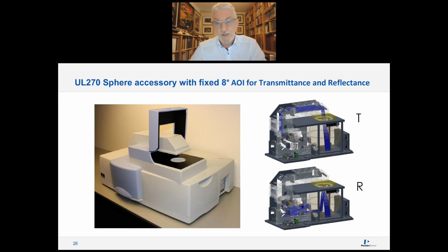First of all, they have both the same angle of incidence. The reason for that is that we found that an important property for comparing cover glasses, with the light absorption in the glass determined from transmittance and reflectance, is that the measurements should be at the same angle of incidence. Otherwise, if you have very low absorption, you can even get negative absorption coefficients. If you say 100% minus the transmittance minus the reflection is the absorption, then it doesn't fit very well. So they have the same angle of incidence.